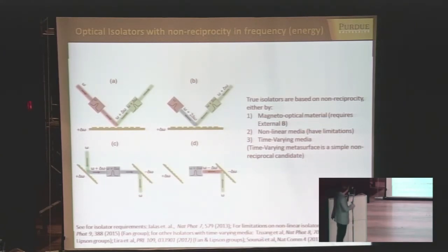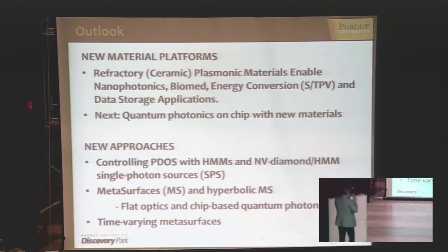So basically, if you have an optical cavity formed by two metasurfaces which change phase in opposite directions, if light goes from here, the shift of frequency is omega plus delta omega, and it's supported by this cavity, it would go out. But if you move in the opposite direction, since this metasurface shifts the phase in the negative direction, the frequency omega minus delta omega is not supported by this cavity, it would not go out. This is non-reciprocal light.